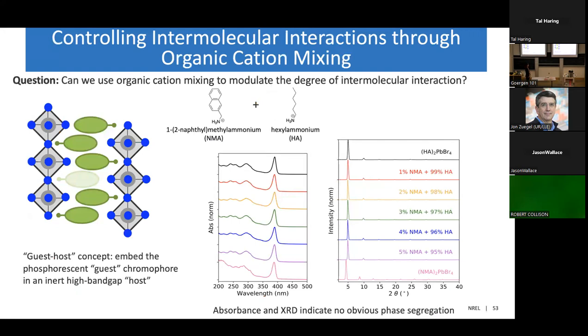All right, so here we borrowed a concept that's often used in organic electronics called the guest-host concept, where if you have a phosphorescent guest emitter, you surround it with an inert molecule, really inert high band gap molecule, in order to protect this chromophore from unwanted quenching interactions with its environment. So again, we're using naphthalene as our phosphorescent molecule, but we're surrounding it with a lot of this saturated alkylamine, hexylamine, in order to protect it from some of these intermolecular interactions.